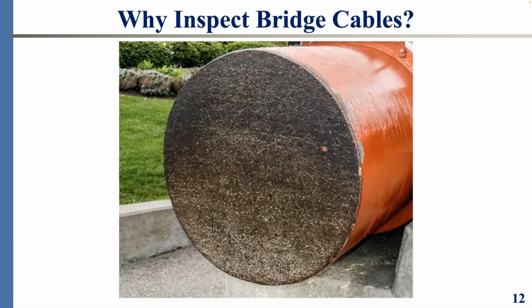Over time, these wires would degrade to different degrees of deterioration in terms of embrittlement. We'll see what that means. Plainly put, that is the loss of ductility. They will have cracks. Some of the wires will break. So a proportion of the cable cross section you see, in general, not this particular one, will have a proportion that's broken, a proportion that's cracked, and a proportion that is degraded with embrittlement and loss of ductility. That means loss of ductility and loss of strength.